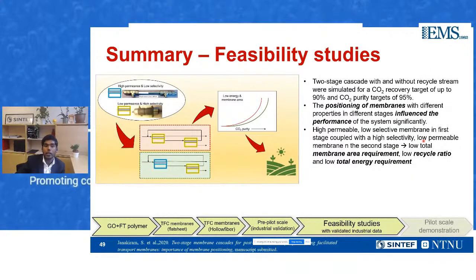So here we have shown that a two-stage cascade with and without recycle can be used for purifying CO2 and reaching a target of CO2 purity over 95%, at the same time with a recovery of 90%. And in this case, we also have proved that the positioning of membranes of different properties in the different stages is very important and can influence the performance of the system significantly. High permeable membranes, which are low selective membranes, in the first stage, when coupled with high selectivity membranes in the second stage, are proven to be the best system under these conditions.